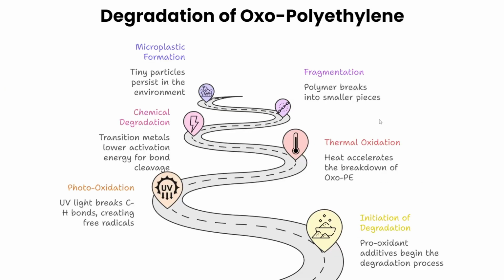Degradation process of oxo-PE. The degradation of oxo-degradable polyethylene involves breaking the polymer into smaller fragments and simpler components through chemical, thermal, photooxidative, and microbial processes facilitated by pro-oxidant additives. Photooxidation occurs when UV light breaks carbon to hydrogen bonds in the polymer, creating free radicals. These react with oxygen to form peroxyl radicals, leading to chain scission, reduced molecular weight, and the formation of carbonyl groups, aldehydes, and ketones. Over time, the polymer fragments into smaller pieces, eventually converting to carbon dioxide and water.